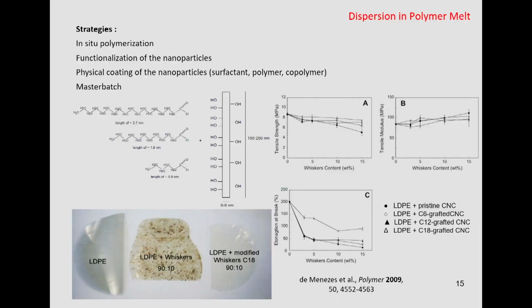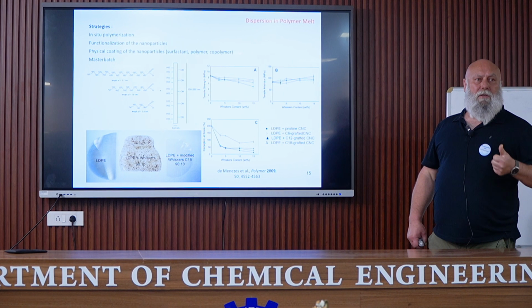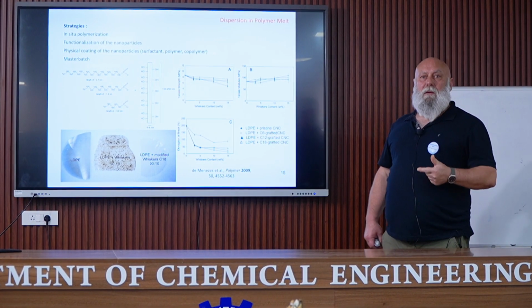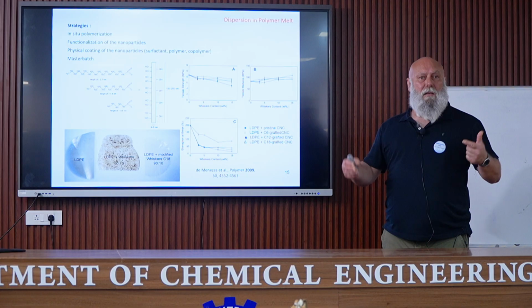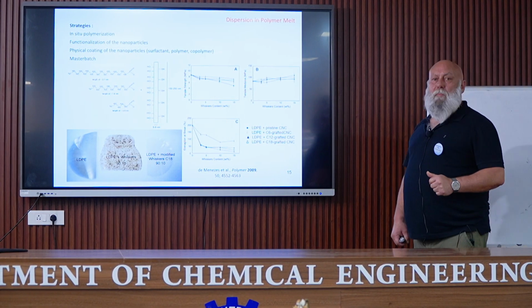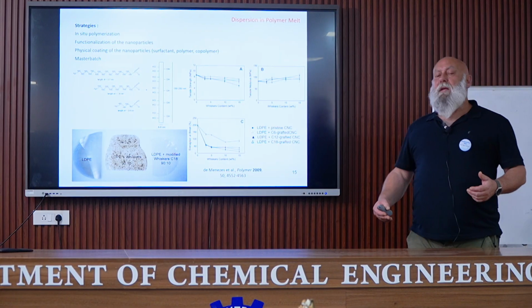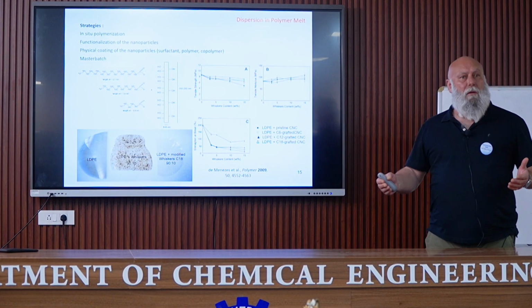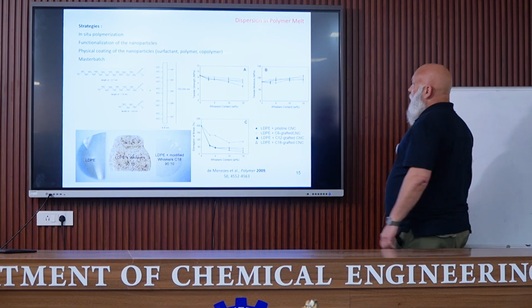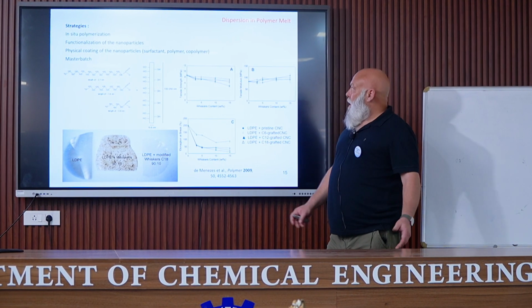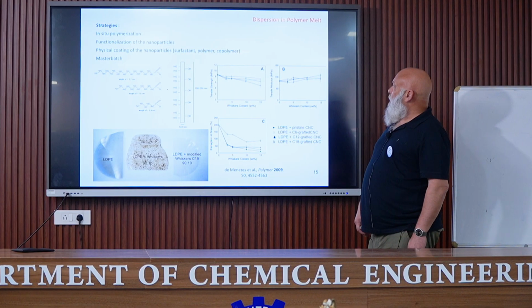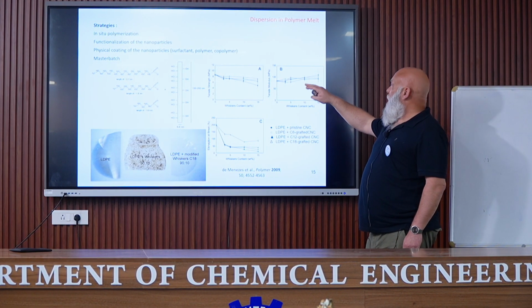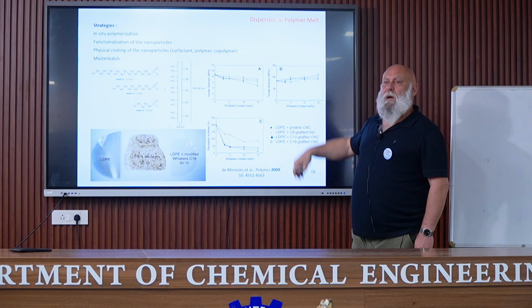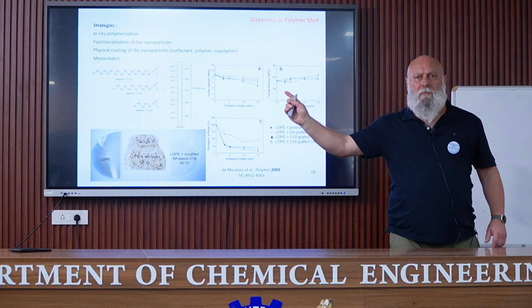Now the dispersion in polymer melt. What is possible? In situ polymerization, meaning that the nanofibrils or the nanocrystals are mixed with a monomer, and then in situ, the polymer can be polymerized. We should have a better dispersion in a liquid than in a polymer melt. Functionalization of the nanoparticles, again, physical coating of the nanoparticles with a surfactant, polymer, a copolymer, or a master batch. You know what is a master batch?